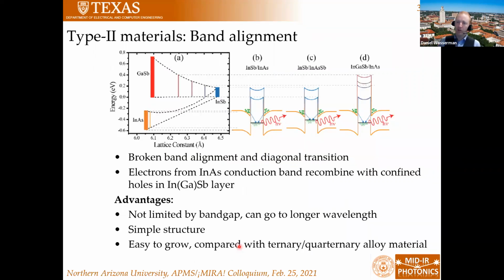But what we can start thinking about is what's called type 2 materials. So type 2 materials are a little bit different. They have a band alignment where the valence band of material 1 sits above the conduction band of material 2, which means that you can make a quantum heterostructure here where your holes are confined in material A and your electrons are in material B. And what you essentially have is this diagonal transition between B and A. And by tuning this geometry, you can effectively tune the position of the valence band state right here.